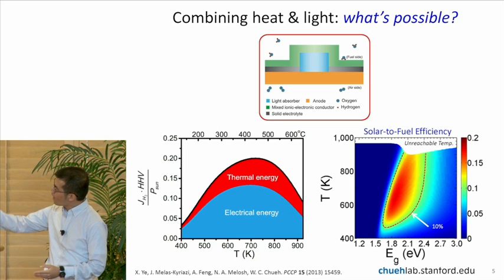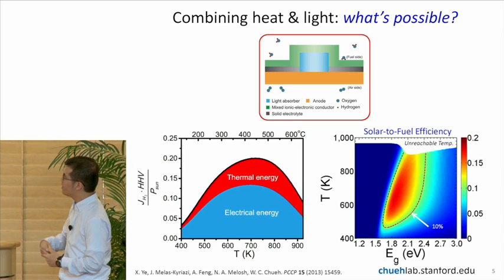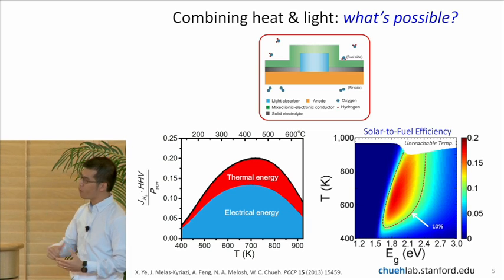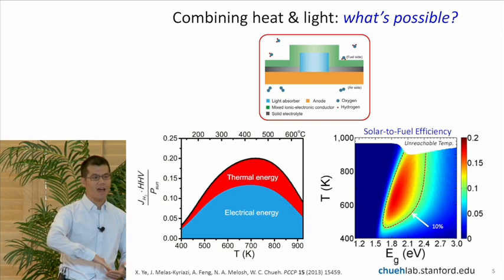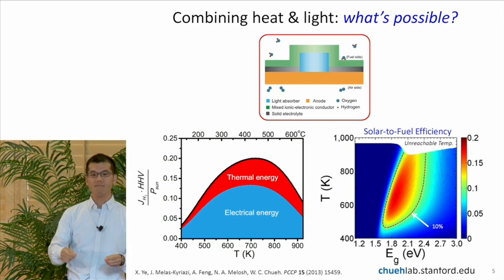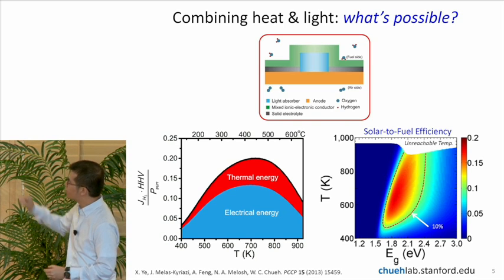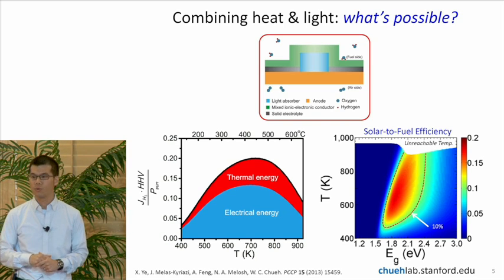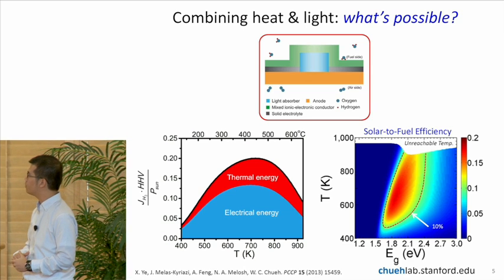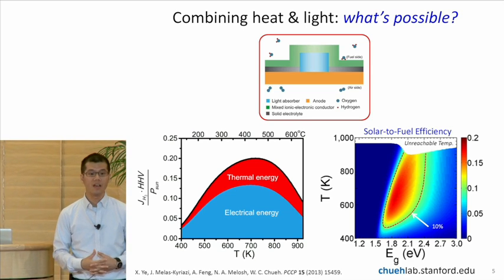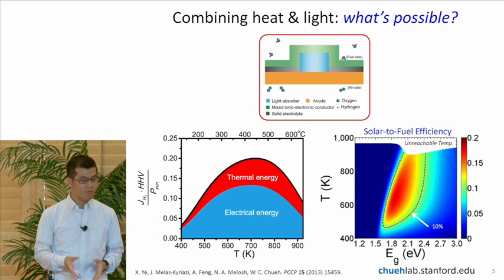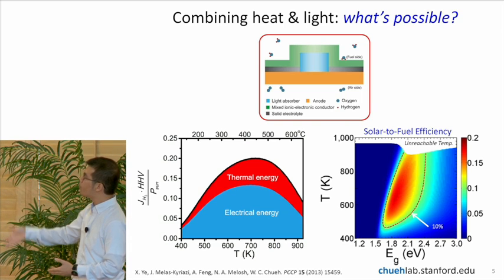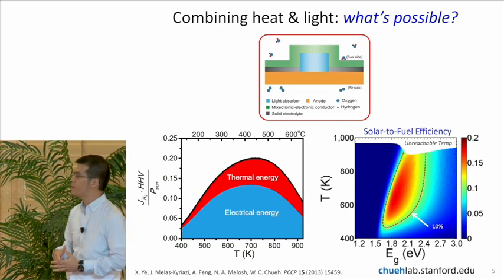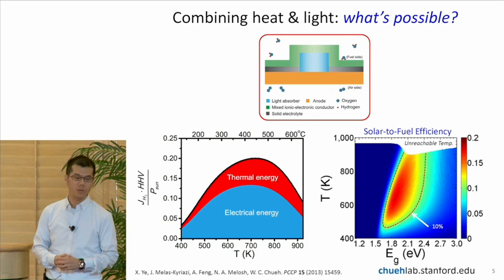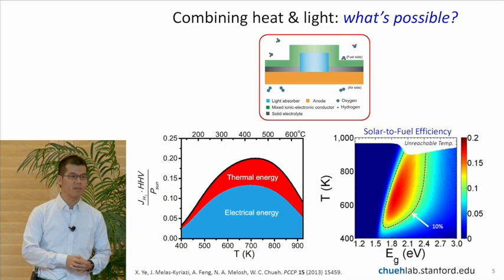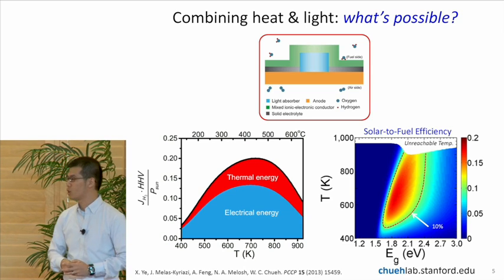So you can see the y-axis is essentially the efficiency you can hit. As you go from room temperature to 400 degrees C to 500 degrees C, you have a significant rise of the efficiency, and most of it actually comes from an increase in the thermal contribution to the amount of energy stored in the fuel. We also looked at it as a function of material properties. So the plot on the right is a parametric plot of the operating temperature in Kelvin and the band gap of the material. And the color shows you the predicted efficiency of the system, accounting for various loss terms.